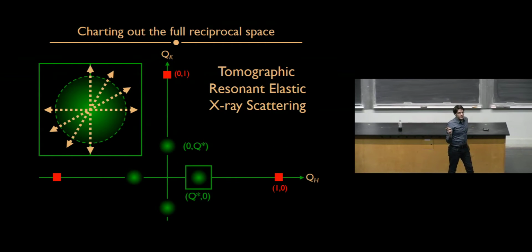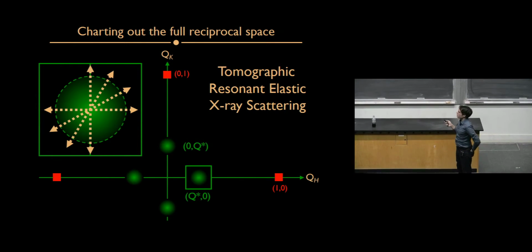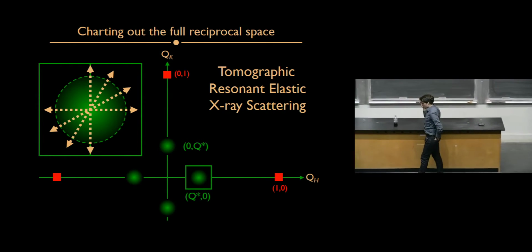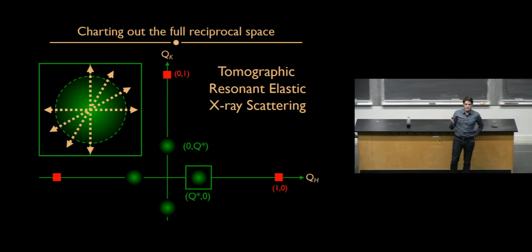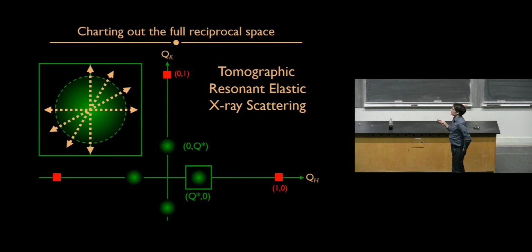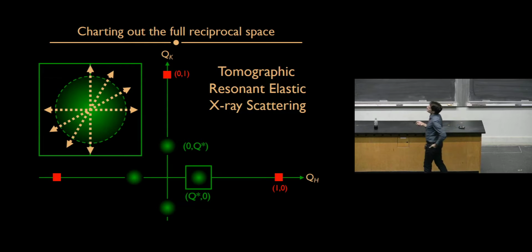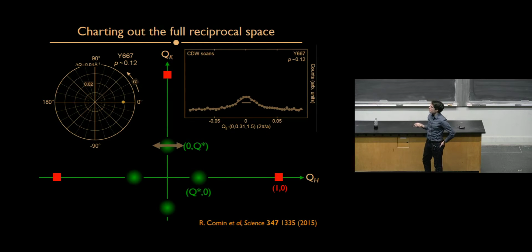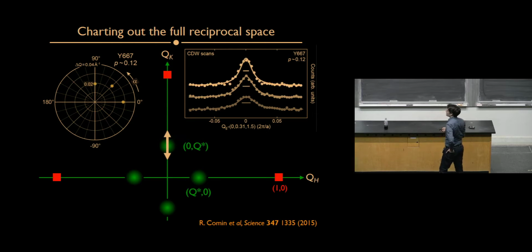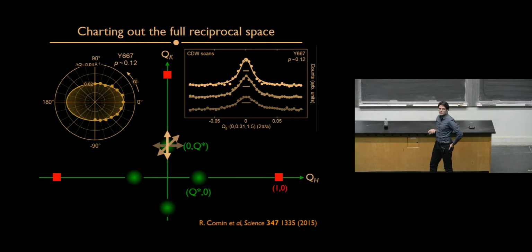So we went ahead and did this kind of experiment in the cuprates. So we sought after resolving the two-dimensional structure of these diffraction peaks that we can see with resonant scattering. So we came up with a name for it, but don't focus on that. It's actually T-Rex if you read it, but it's fine. But it's in a way tomography, right? So we're reconstructing a higher dimensional object by taking lower dimensional slices through it. In this case, we take one-dimensional slices through this two-dimensional peak, and we reconstruct its shape. We have to use a special geometry for doing this. I'm not going to talk about it in detail, but we can do it, bottom line. So we can get these different profiles, and we can reconstruct the shape of this peak in reciprocal space.